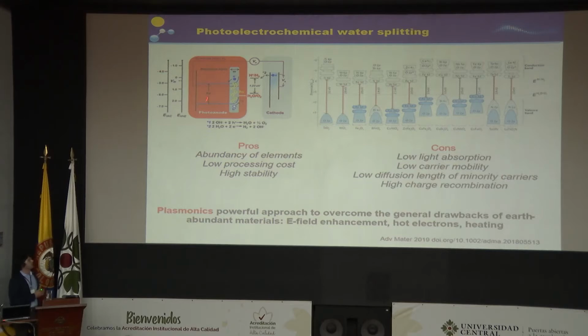As you can see here, the mechanism of function is basically similar to a photoelectric effect, similar to what's going on in solar cells. The only thing which is different is that we have the electrolyte and so the chemicals which are in contact with this semiconductor. And this has really changed everything because, for example, we cannot use silicon or III-V semiconductors, which have very nice performance for photovoltaics. If you use silicon or III-V semiconductors here, we will have corrosion of the devices, and the device will last 10 hours at maximum. That's why there is a big interest in the use of metal oxides, which are also cheaper from a point of view of the processing, and they are much more stable in photoelectrochemical conditions.